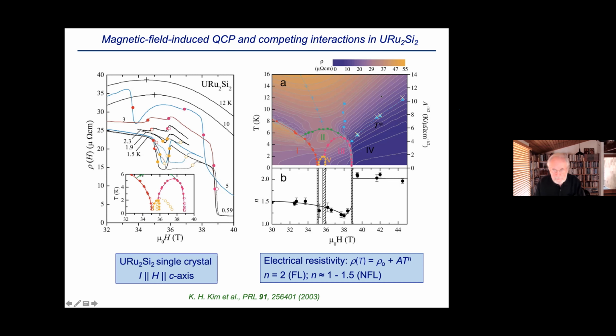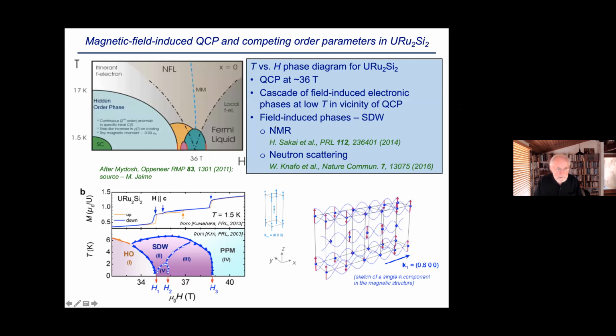So this is very complicated, I realize, but at any rate, you get all these phase boundaries and phases, and it turns out that in this region, in these phases, the exponent of the resistivity is 1.5 or less. So these are all non-Fermi liquid-like phases. And then in this region, this is more like a Fermi liquid. The resistivity has this exponent of 2. Okay, so these are exotic phases, and I think in the next figure you can see this a little bit more clearly. So this is an easier to understand phase diagram in terms of the various features that was, I think, constructed by Marcelo Jaime.